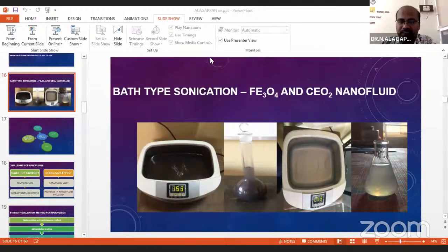This is prepared for my research work. Once I pour the water in the bath type, afterwards I pour Fe3O4 nanoparticles inside the sonication machine. Then I set the time for 1 hour. The machine starts to produce vibration. You can see the vibration here. Due to the vibration, the particles mix with the water properly. After the sonication process, the Fe3O4 material with the fluid is stable for around 45 days. Afterwards, it starts to sediment.